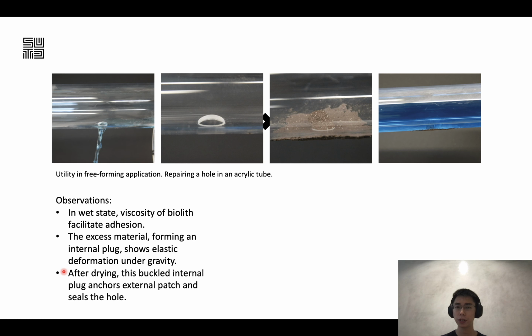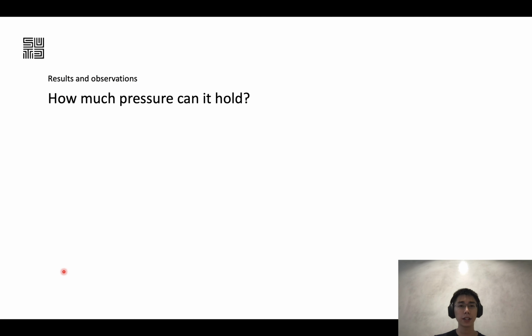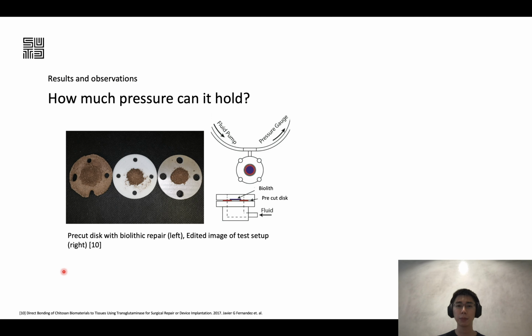Now, the follow-up question that we have is that since it can repair a water-containing device, what is the pressure that this sort of repair could withstand? And in this case, what we did was a modified burst test where different discs with a pre-cut hole in the middle are prepared, and we patched the hole with Biolith. And after drying, we subject it to increasing hydraulic pressure in on-seating and off-seating conditions. On-seating means that the pressure is pushing the Biolith patch against the substrate, while off-seating means that it's pushing the Biolith repair away from the substrate itself.